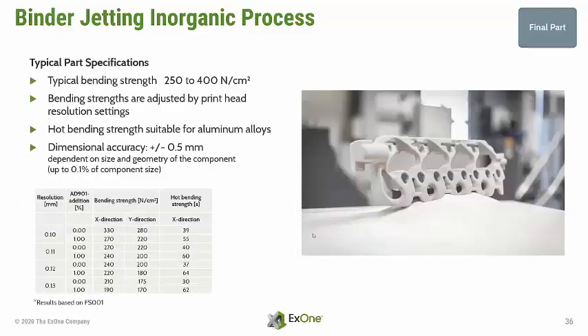Finally, we're getting to the specifications of the final inorganic part. The bending strength gets adjusted prior to the print job by the printhead resolution settings and is typically in a range of 250 to 400 Newton per square centimeter. The hot bending strength is currently lower than at Furan, but very well suitable for aluminum alloys. ExOne is already working with our partners to further improve this.